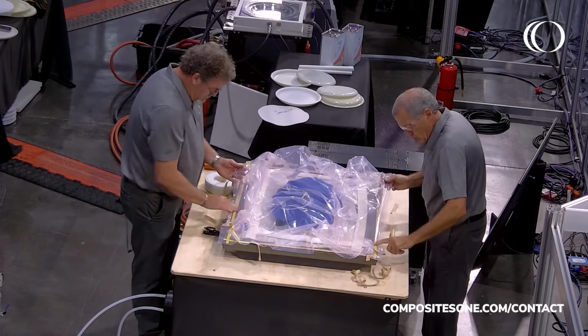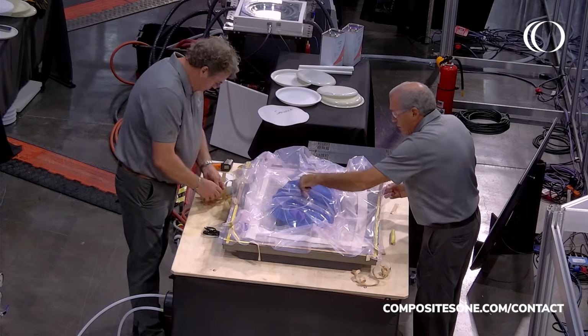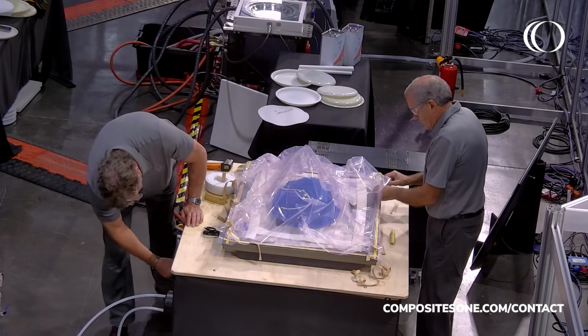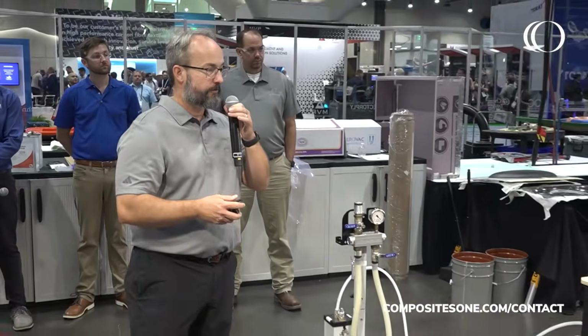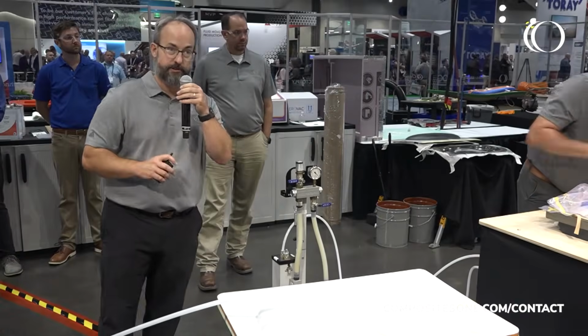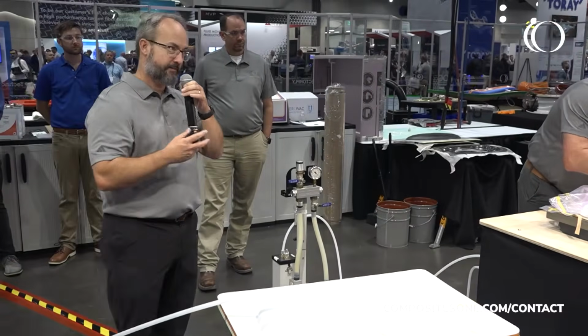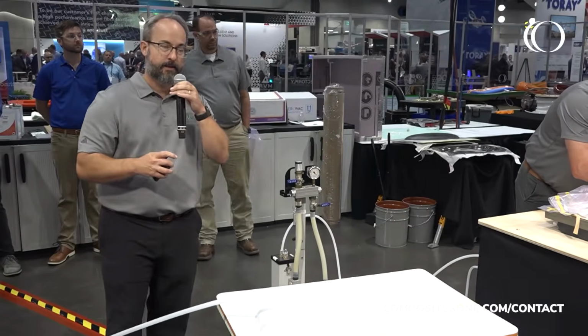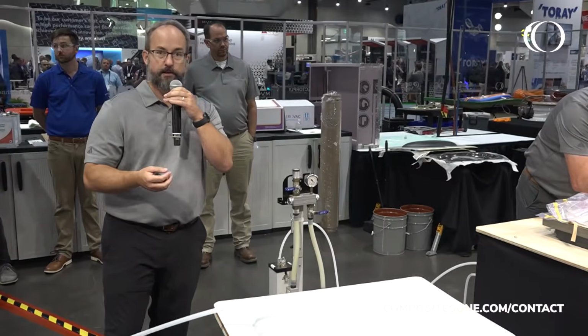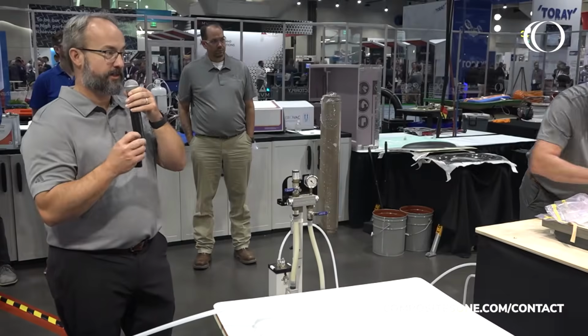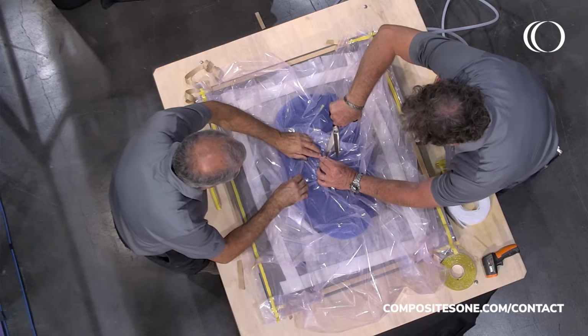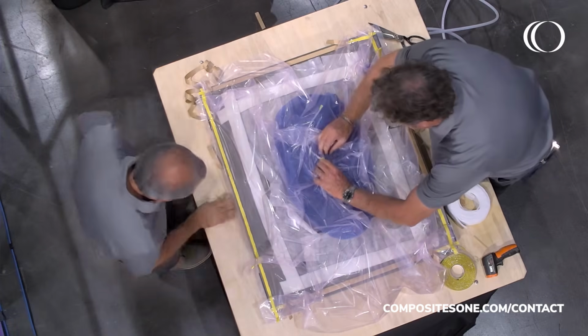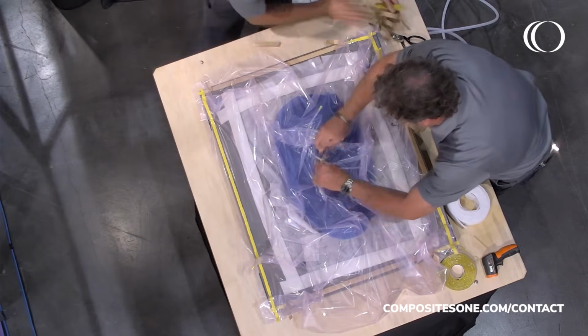Thanks, Doug. A little bit more about the infusion process, if you're not very familiar with it. It's driven by Darcy's Law, which has several different variables: the resin viscosity, the vacuum pressure or atmospheric pressure, and how far we're going to flow. With the temperature-controlled tooling, we actually have the tool set at 90 degrees Fahrenheit. The show hall today is about 75 degrees, so we can warm our tool up a little bit, and that's going to help the resin flow, because the resin viscosity depends on the resin temperature, and in the infusion process, the resin temperature is going to be whatever your mold temperature is. So the higher the temperature, the lower the viscosity, the better flow you're going to get, and the better wet out.